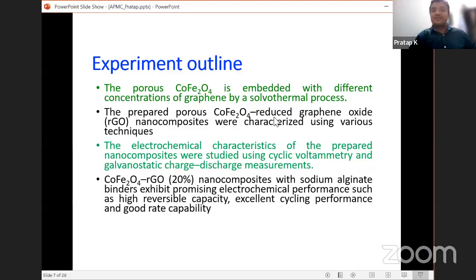The prepared cobalt ferrite materials were characterized using various techniques like XRD, SEM, FTIR, Raman, and TG-DTA to check whether they have formed correctly or not. So this is for structural confirmation. Once we confirmed the structure, the electrochemical characteristics were studied using cyclic voltammetry and galvanostatic discharge. Among all these composites, 20% RGO plus cobalt ferrite showed very good electrochemical performance, very good reversible capacity and excellent cycling performance. So this is the one we are talking about.